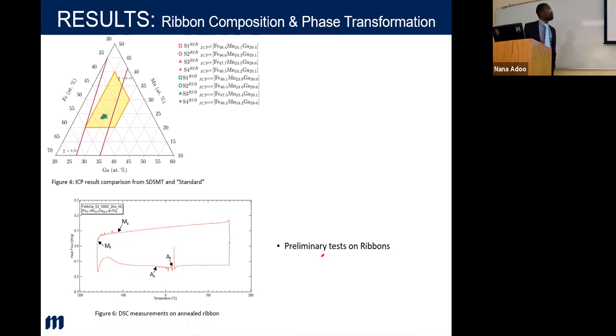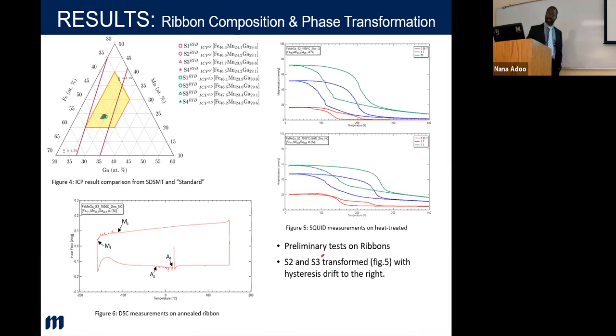These are the preliminary results I did for the ribbons, and then tested them. I had 4 ribbons. I tested 2, and they all showed this transformation. And then I did a SQUID test on them. These were actually sent to another external laboratory to test it.